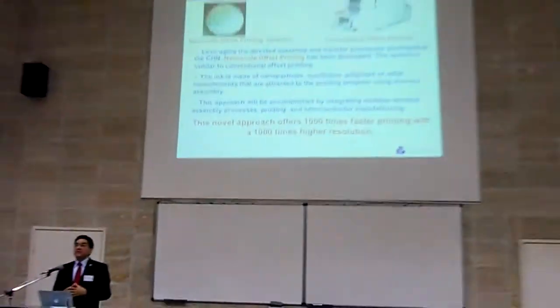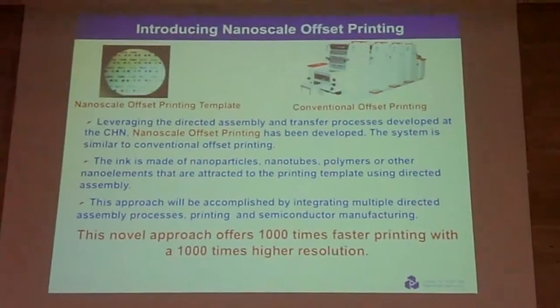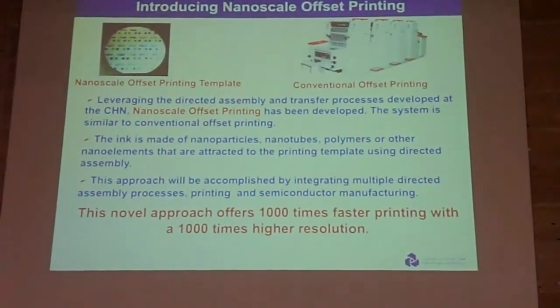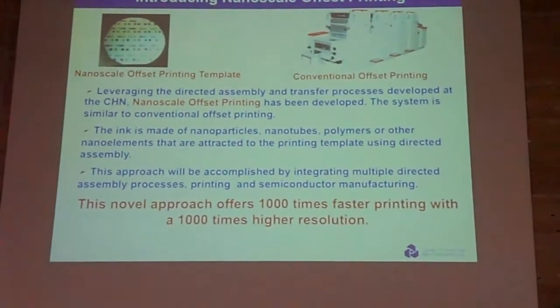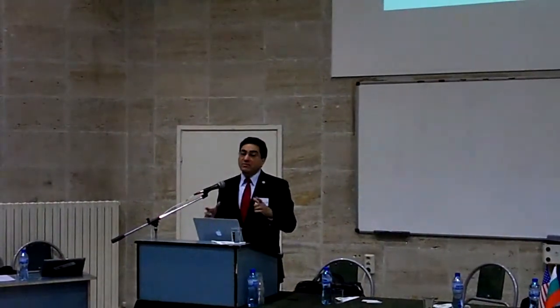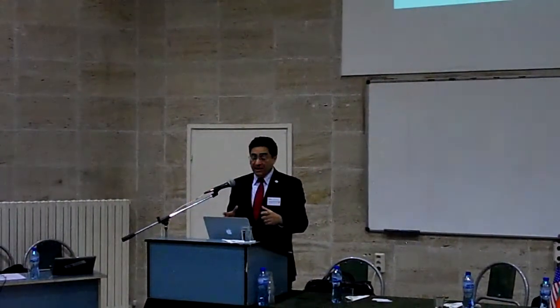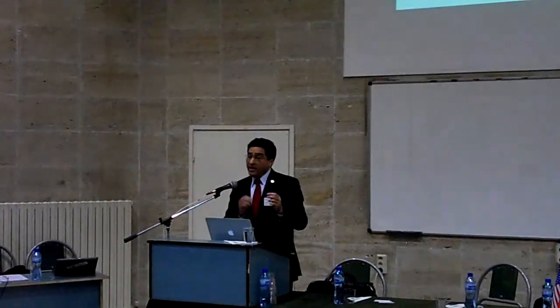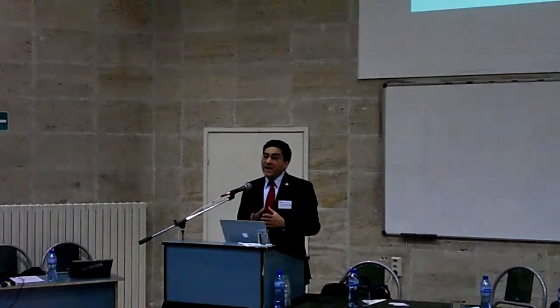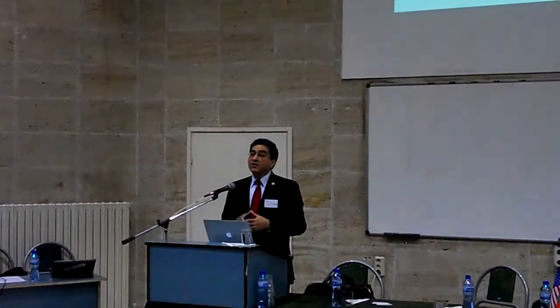We developed special templates with which you can print nanoscale structures from conductors, semiconductors, or insulators. And we call it nanoscale offset printing. You can use any kind of nanoparticles, nanotubes, polymers, a variety of things. In this approach, we make the template using conventional semiconductor fabrication. I'm going to show you examples of that. And we use directed assembly to ink, or to apply the nanomaterials, to the template, and then we transfer. This approach gives us 1,000 times faster printing than current technology, and 1,000 times smaller structures than current printing technology.